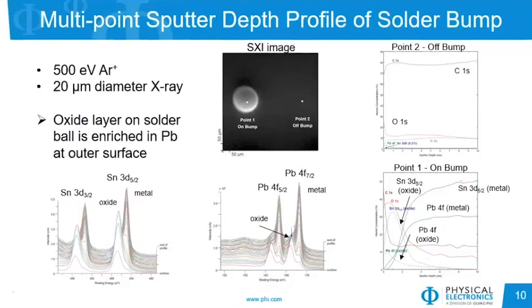Now looking at a metallic sample with the monoatomic argon, this is an example of a multi-point sputter depth profile on a solder bump. Now in our SXI image, which you see at the top center, this is a secondary electron image that was collected by scanning the X-ray beam, and we have a bright region which corresponds to our solder ball, and then a darker region which corresponds to the surrounding area. We can select points directly on this image to choose where we want to do our profiling. And so the spectra that you see below are from the solder bump itself.